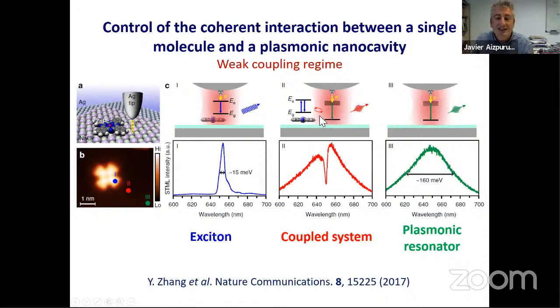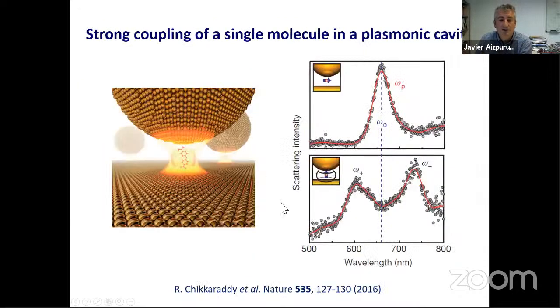Why? Because the dipole of the molecule is aligned perpendicular to the local field of the cavity. If we manage to put the point dipole aligned with the local field of the cavity, then we could get a strong coupling. And actually, this is what the group in Cambridge of Jeremy Baumberg did in this situation. Right? They have this nanoparticle on a mirror, and they managed to put this methylene blue, which is an emitter, inside a barrel, a cucurbituril organic molecule, with the dipole pointing upwards.